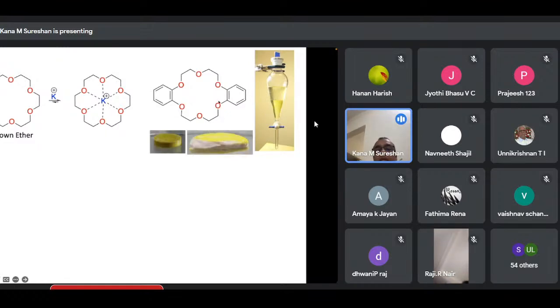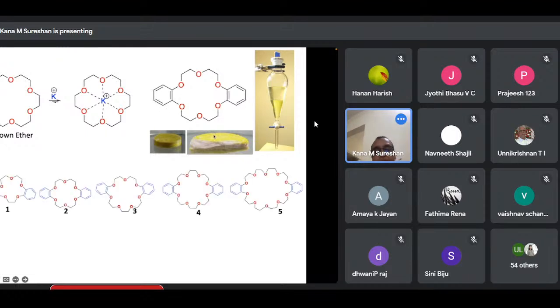So this is what I said. If you make a pellet out of this solid, of course, if you put in potassium picrate, the color is because of the potassium picrate. What you see is that potassium picrate is absorbed only on the surface. Once you cut the tablet, you can see most of the inside is unaccessed by the potassium. So this is not very efficient.